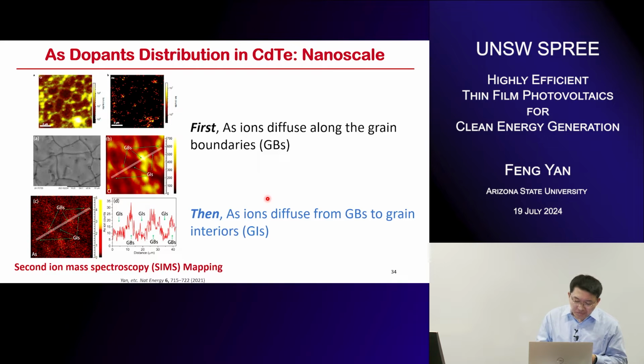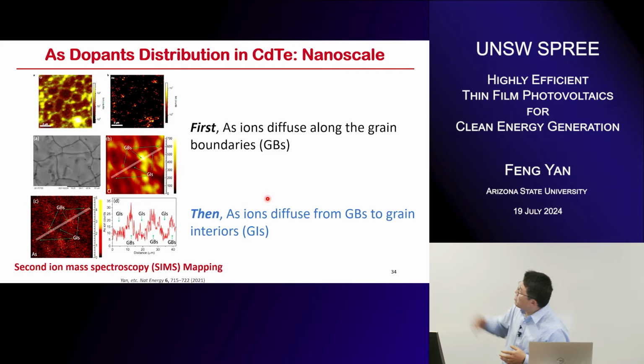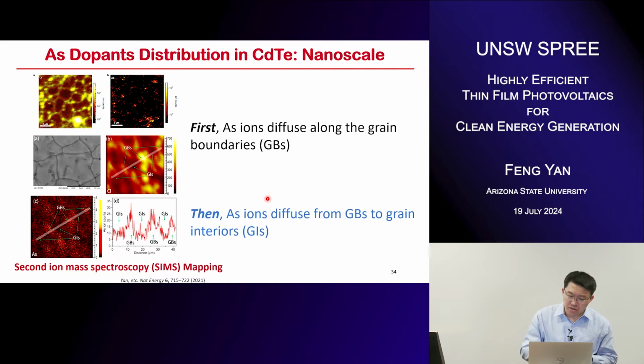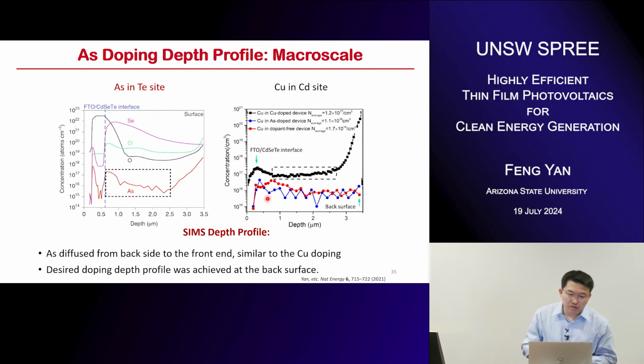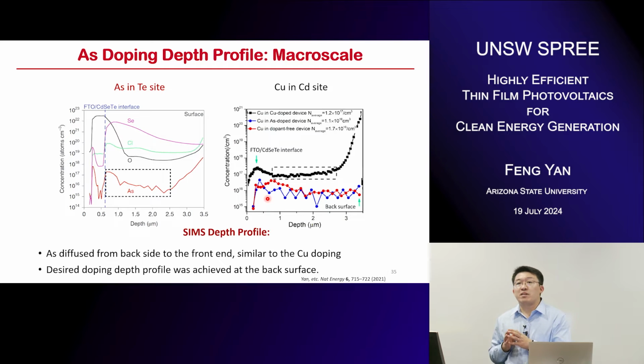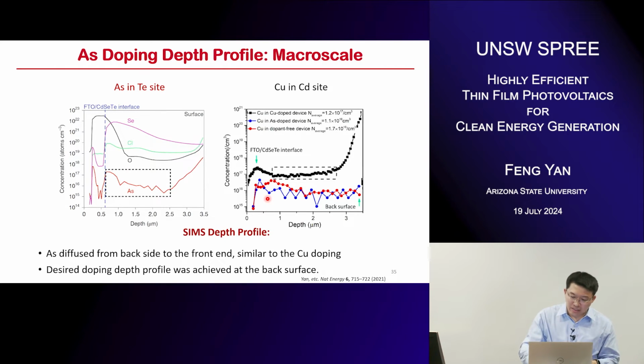which was demonstrated using the secondary ion mass spectrometry two-dimensional mapping. Further characterization demonstrates a similar diffusion profile when comparing arsenic and copper. You can see that the arsenic is very heavily doped on the back side and lightly doped in the front side. So this is the desired doping profile to achieve a better back surface.